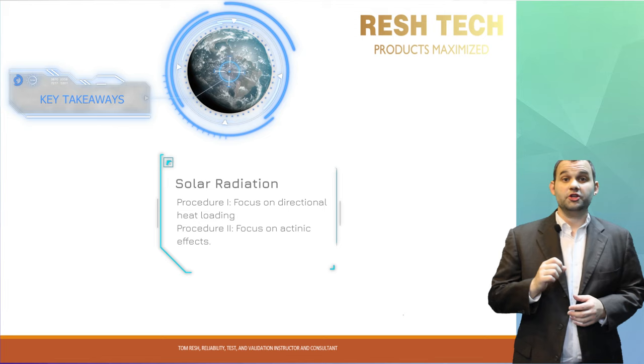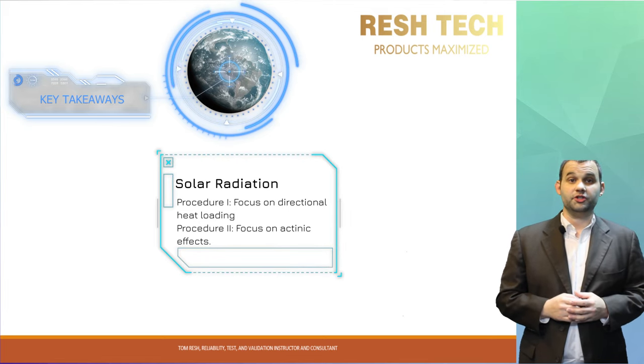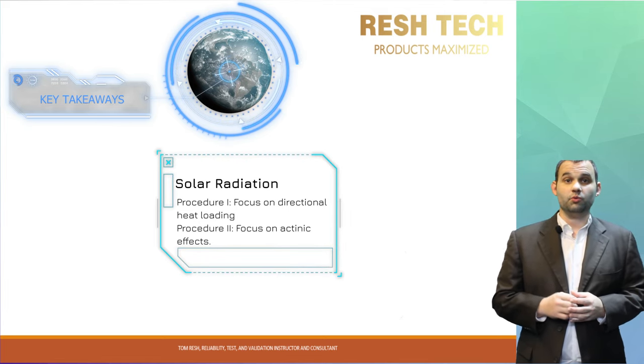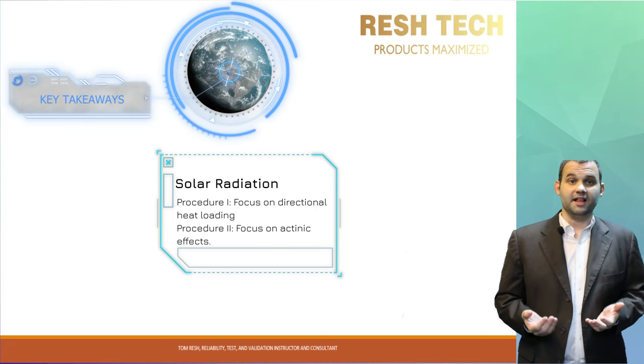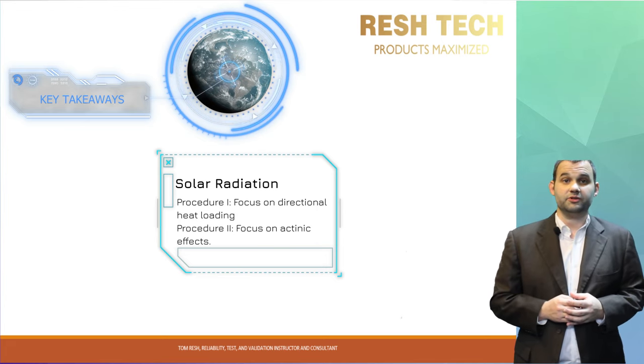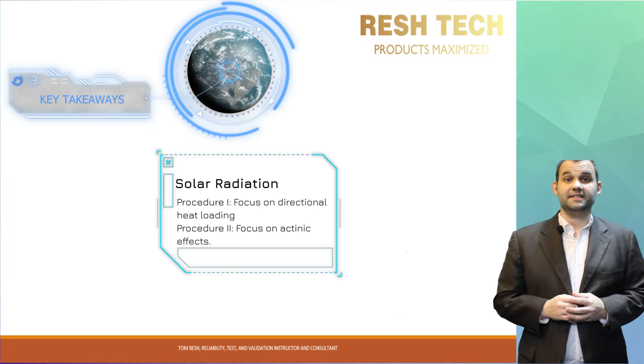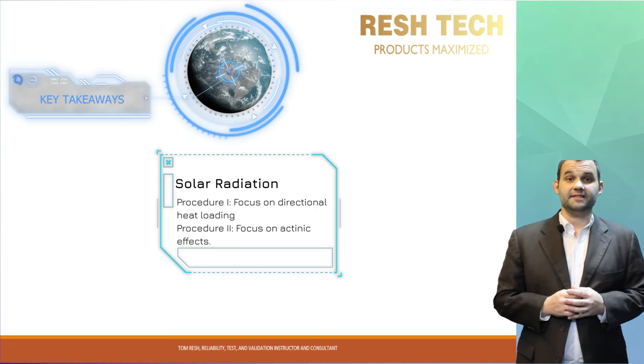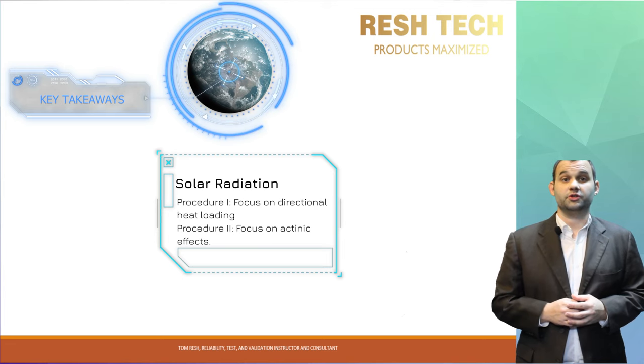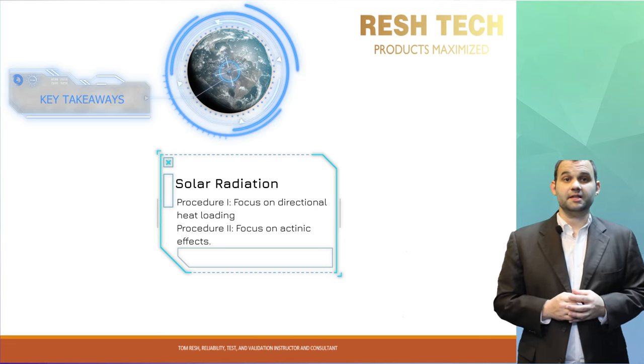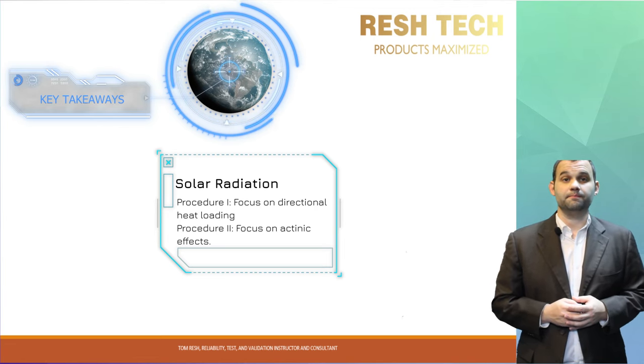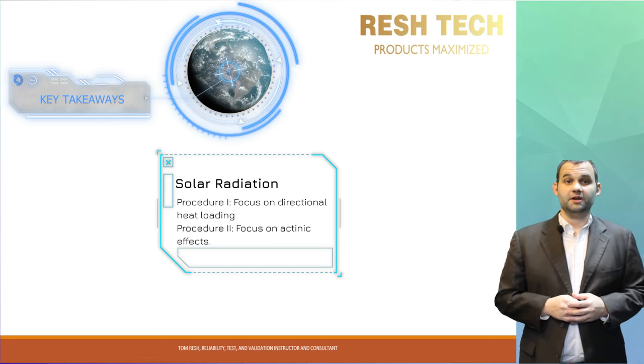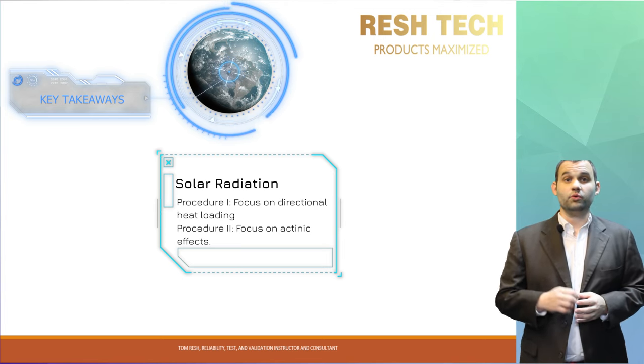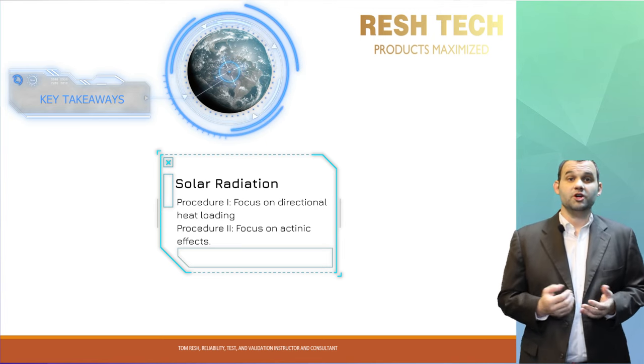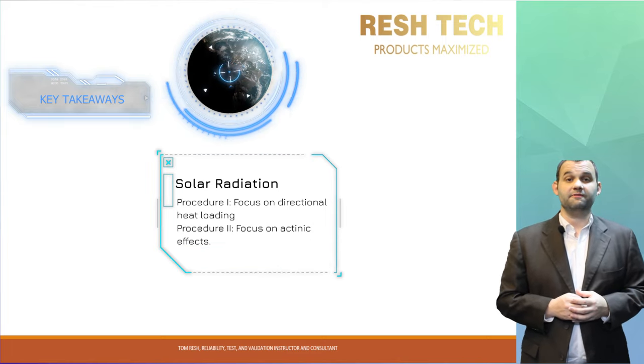The two types of tests we covered in procedures 1 and 2 have different intent, with procedure 1 being more of a heat loading and analysis of temperature gradient effects on your system, and procedure 2 being a test that looks for actinic effects that may occur with your system's exposure to direct sunlight. Both tests can be accelerated to reduce test time or to simulate a longer span of mission time or field time. But you need to be careful not to accelerate the test to a point where the results are unrepresentative of what your system would endure in field operation.